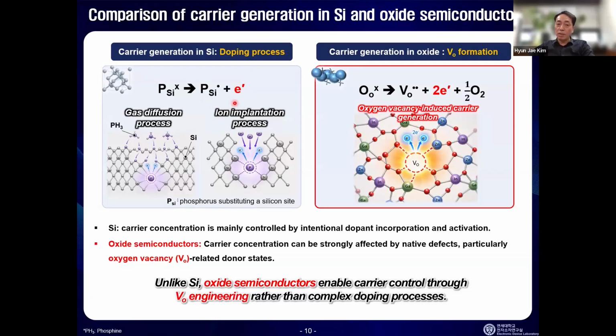Okay, one more time, for a silicon semiconductor, you have to put in some material. This is phosphorus. You put in the phosphorus, it has one extra electron, so it generates an electron, and this becomes an N-type semiconductor. But for the oxide semiconductor, you don't ion implant. The defect is the oxygen vacancy. When you have an oxygen vacancy, automatically you have two electrons. So oxygen vacancy means two electrons. Okay, so a different mechanism.